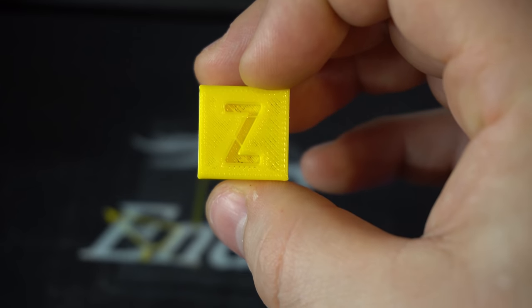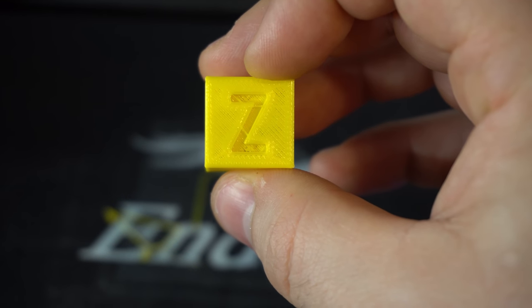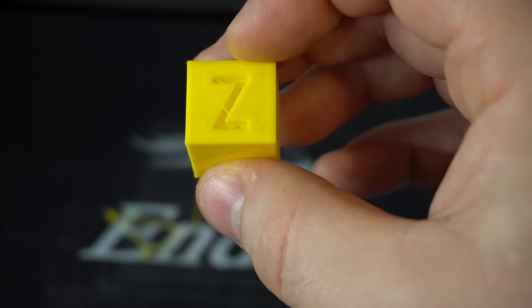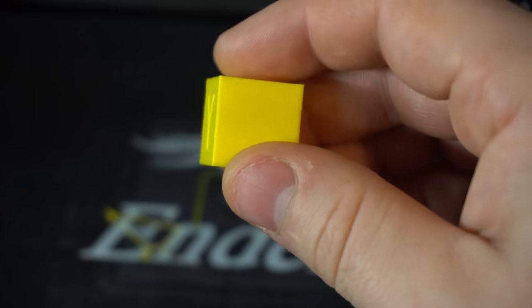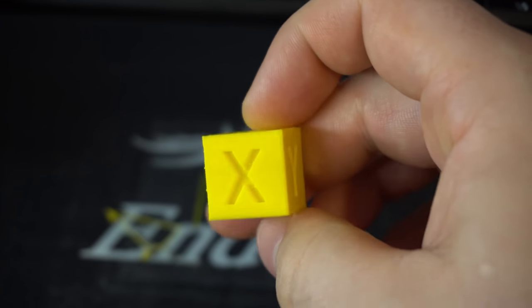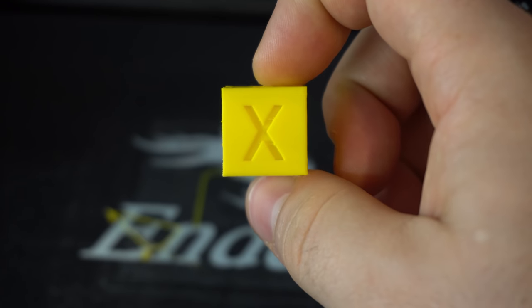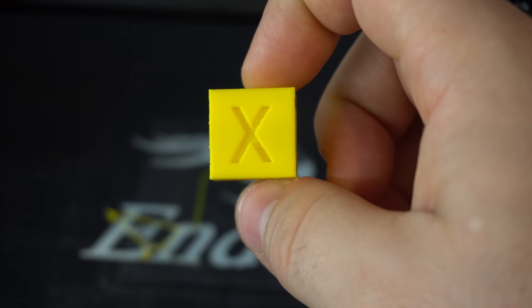All right and here we have our finished print. What I did was I reduced the retraction that I was using which was five millimeters down to three millimeters and it looks like everything came out perfectly. Super pleased, no signs of under extrusion, just right. A little bit of stringing on the inside there so we'll work on that a little bit more but otherwise this is pretty darn good print. Now let's load in the fun stuff. I'm gonna go with NinjaFlex.